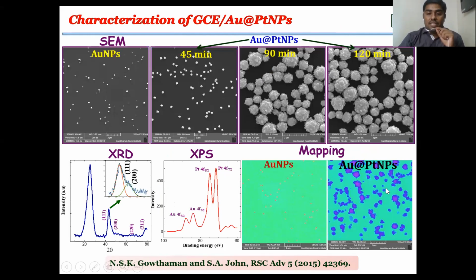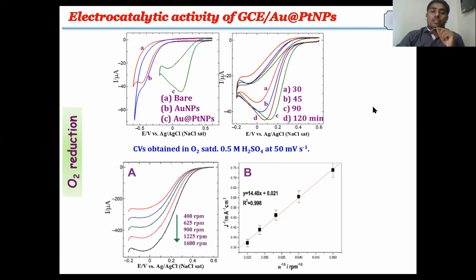From the mapping images, we find that gold and platinum nanoparticles are fabricated on the electrode surface. So we utilize the electrode for the O2 reduction. Here, the gold platinum bimetallic nanoparticles fabricated electrode exhibited higher catalytic activity by shifting the O2 reduction potential towards more positive potential and with enhanced reduction current.